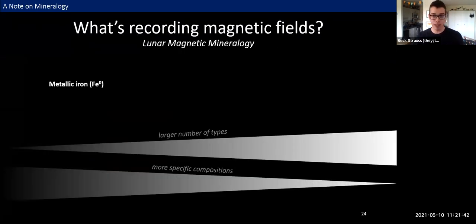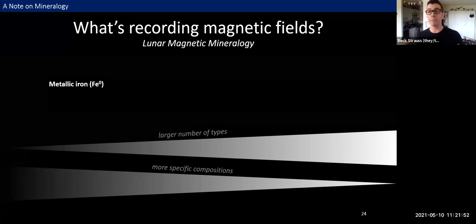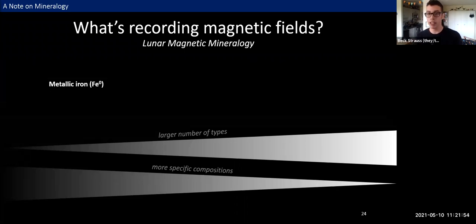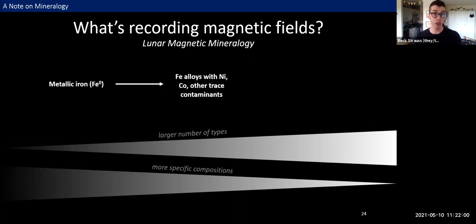Now, for some perspective, when we think about what's recording magnetic fields on the moon, we have to look all the way back to the Apollo era. Early studies of Apollo samples indicated that their ferromagnetic mineralogy was dominated by metallic iron, Fe. This understanding was later expanded to include both iron metal and iron alloys with nickel and cobalt and other trace contaminants. And at that time, the most commonly found form was recognized as kamacite, which is a body-centered cubic iron nickel alloy mineral.